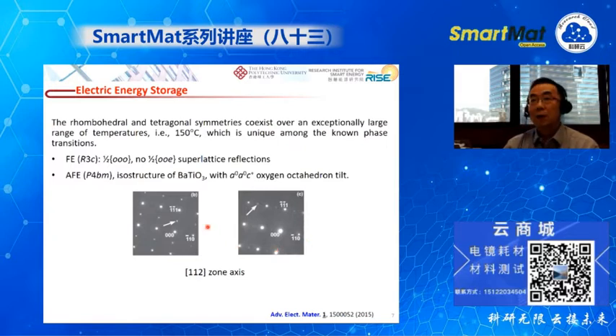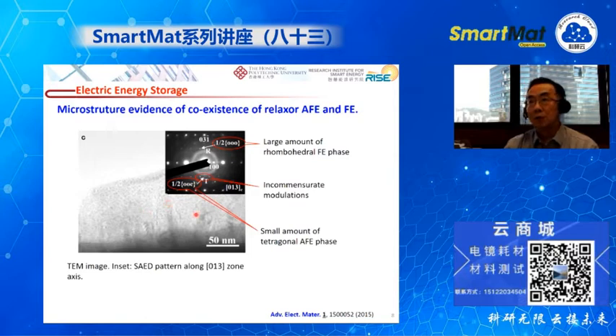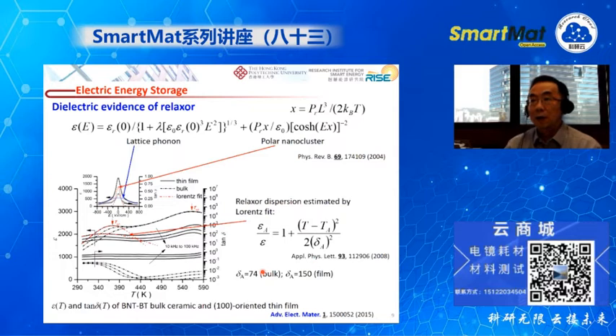So based on this kind of knowledge, we can do a detailed microstructure characterization, and we do find the 2 types of superlattice fringes exist. You can see we found all the odd index superlattice, and we can also find the superlattice for the 2 odd and 1 even index. This corresponds to antiferroelectrics, and this corresponds to the ferroelectric phase. So from TEM, we observed the coexistence of the FE and the AFE phases. And also we found some streaks along this direction, and this is a feature of the so-called incommensurate modulation, and it reflects the relaxor property of the material. So this material also contains a relaxor phase, which is the so-called polar nano region.